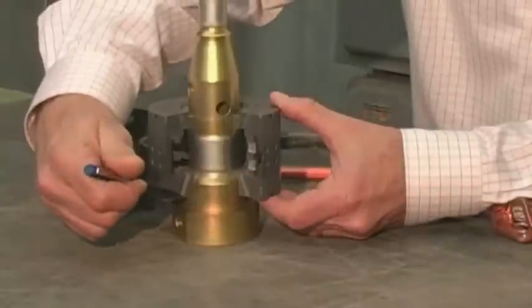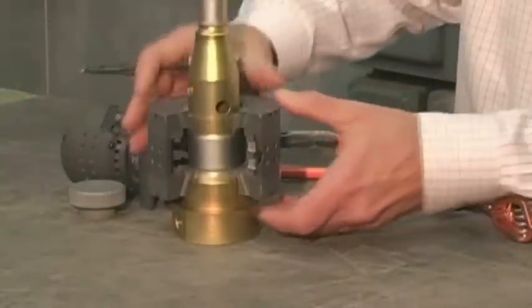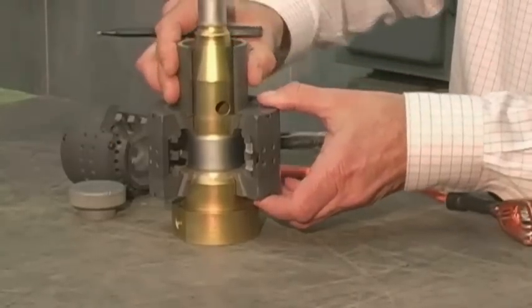The housing encases the electroplating process. It creates kind of a mini plating cell. All the plating activity takes place within that area. The rest of the part is not electrically communicating with that anode, and therefore doesn't need to be masked. And that's how the tooling gets its name.